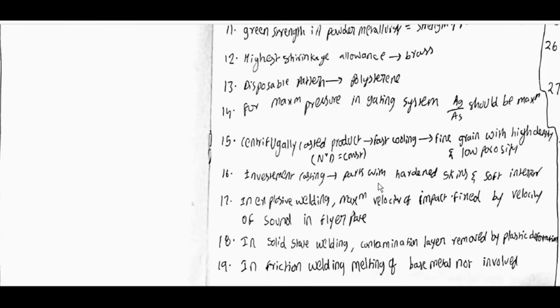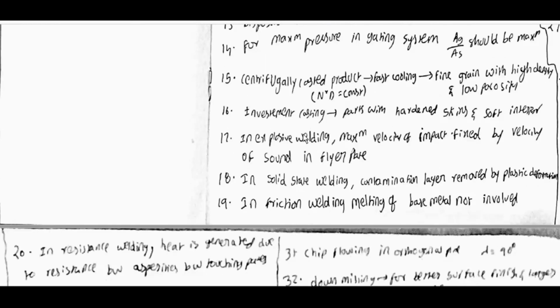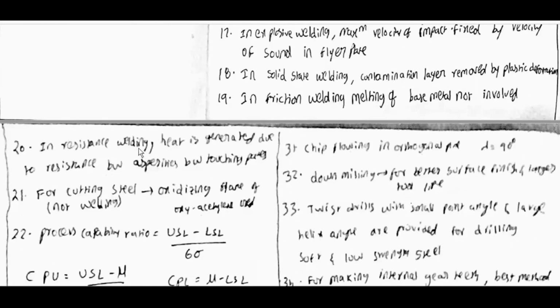Investment casting parts with hardened skins and soft interior. In explosive welding, maximum velocity of impact is fixed by velocity of sound in flyer plate. In solid state welding, contamination may be removed by plastic deformation. In friction welding, melting of base metal is not involved. In resistance welding, heat is generated due to resistance between asperities between touching plates.